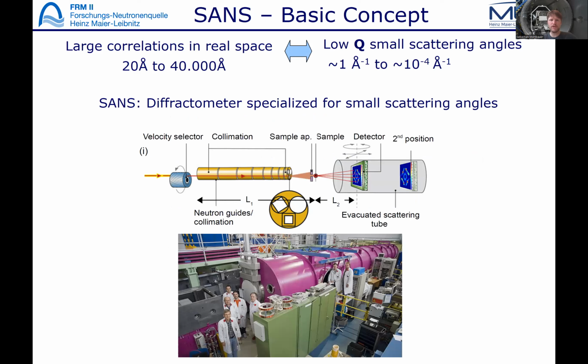So we'll briefly start with the basic concept of small angle scattering. So as you all know, if you want to look at large correlations in real space, so the nanoscale regime, let's say 20 angstroms to around 40,000 angstroms, that goes along with very, very small scattering angles if you just look at Bragg's law, and therefore goes along with small momentum transfers, Q, so in the range of 1 reciprocal angstroms to 10 to the minus 4 reciprocal angstroms. And so small angle neutron scattering, that's nothing else than a very special diffractometer that is specialized to resolve these very small scattering angles. So the scattering angles then range typically from 20 degrees or 30 degrees down to 0.01 degree. If you take typically cold neutron wavelengths of 3 to 12 angstroms.